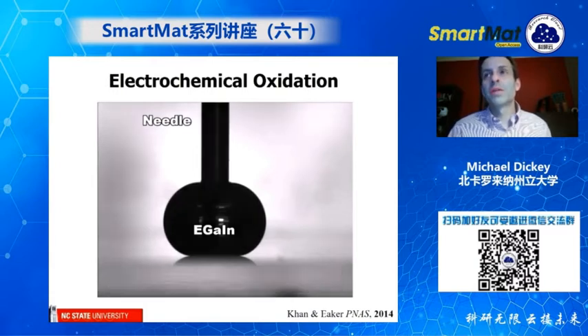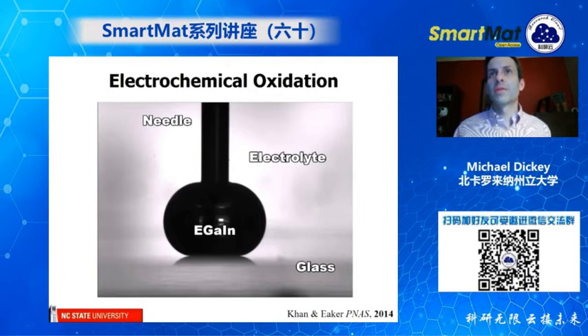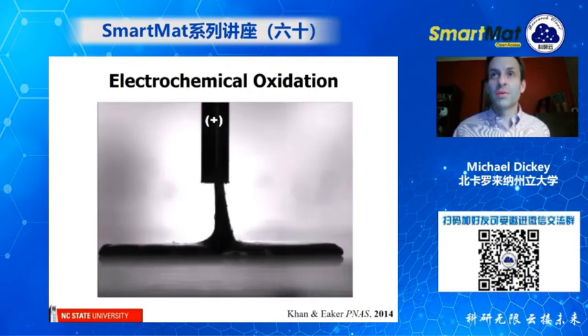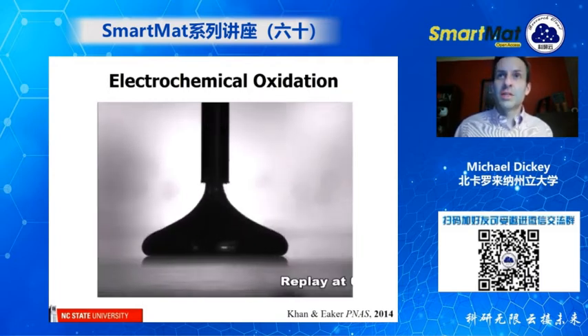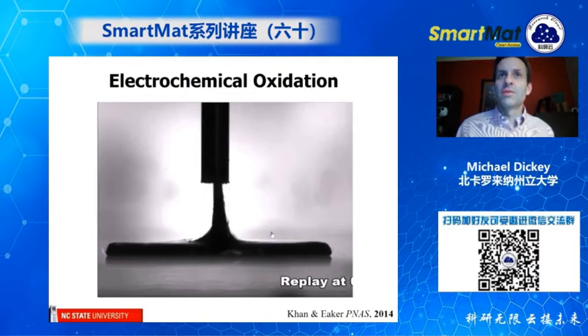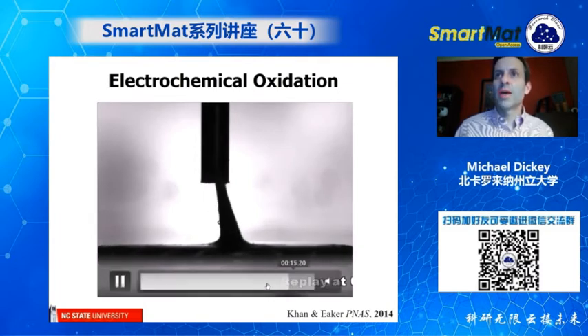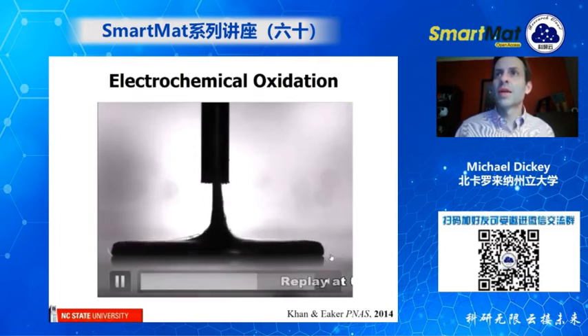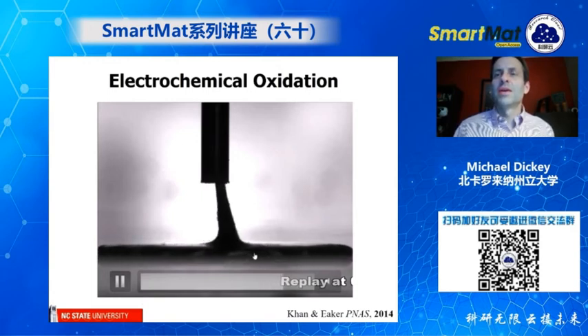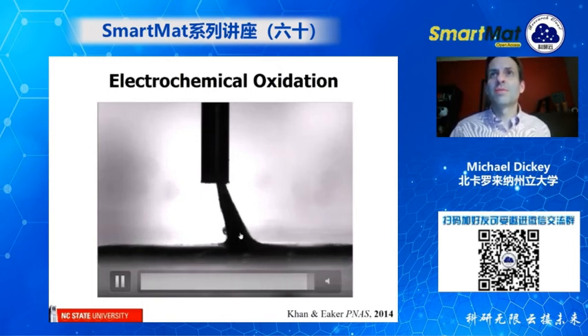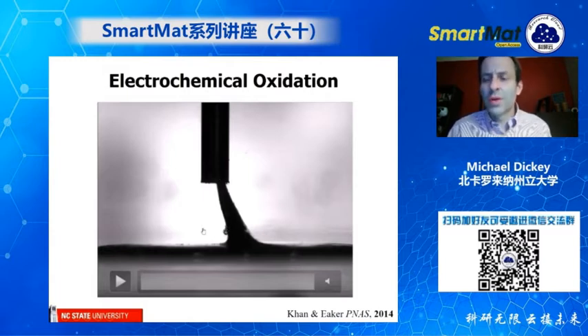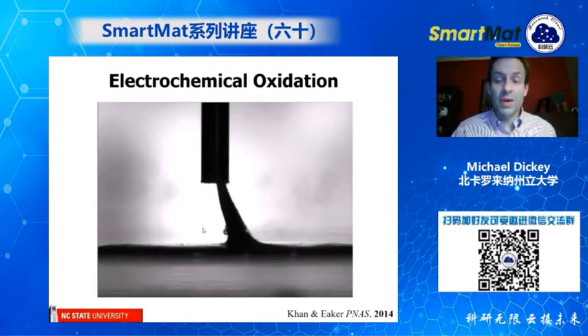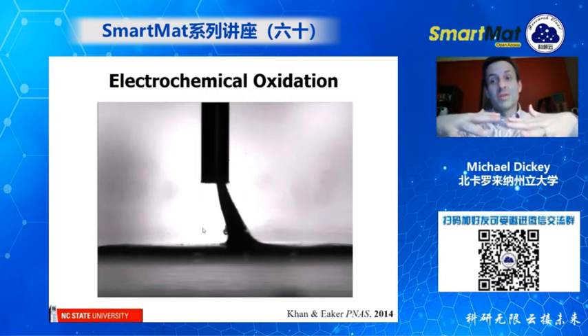But when we do this, we found something very remarkable. And that is that the metal spreads like crazy. It actually flattens like a pancake. And if you look carefully at this leading edge, let me back up a little bit, you can see that it's actually not really wetting. It doesn't have a wetting contact angle. And this forms this weird bridge with this needle, and there's stuff on the surface. There's so many weird things here. But the weirdest part about it is the fact it's flat, because liquid metals have enormous surface tension.